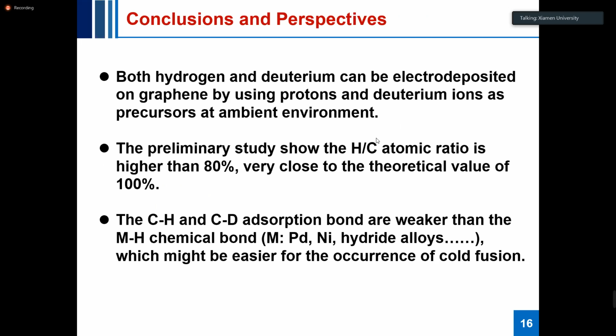We show that both hydrogen and deuterium can be electrodeposited on graphene by using protons and deuterium ions as the precursors at ambient environment. The preliminary study shows that the hydrogen-carbon atomic ratio can be higher than 80%, very close to the theoretical value of 100%. And the carbon-hydrogen and carbon-deuterium adsorption bonds are weaker than the metal-hydrogen chemical bond, which might make the occurrence of cold fusion easier.